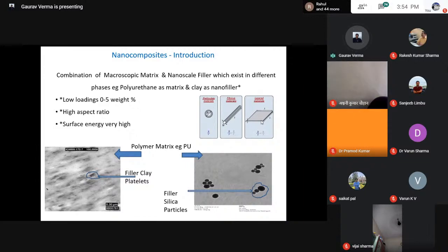The only caution here is, when these materials have an individual existence as a nanoscale material, not as aggregates or agglomerates, then only can the efficacy in changing the properties of the matrix be realized. Otherwise, there will be only incremental changes in the matrix you are encountering. Now, this is something very significant which you should understand.